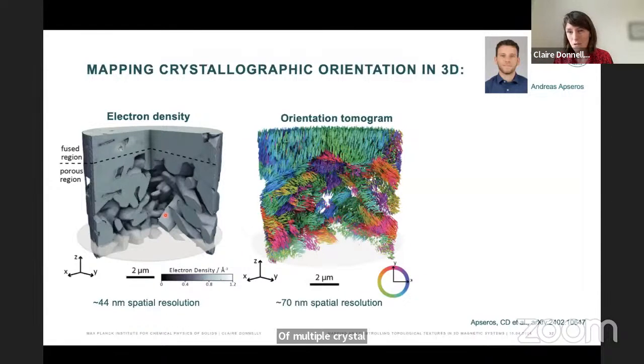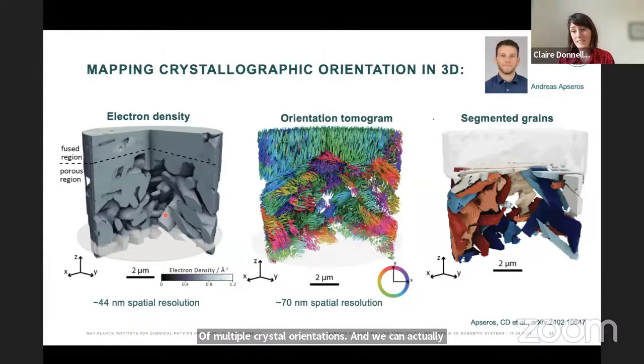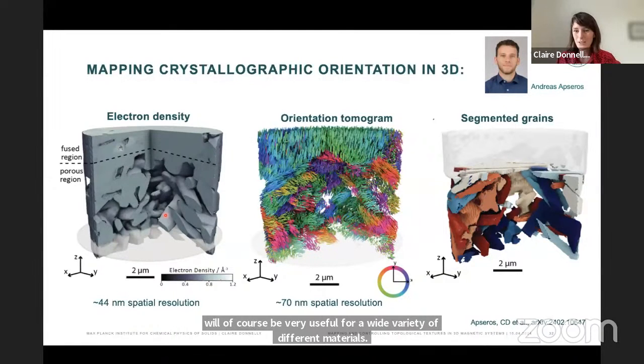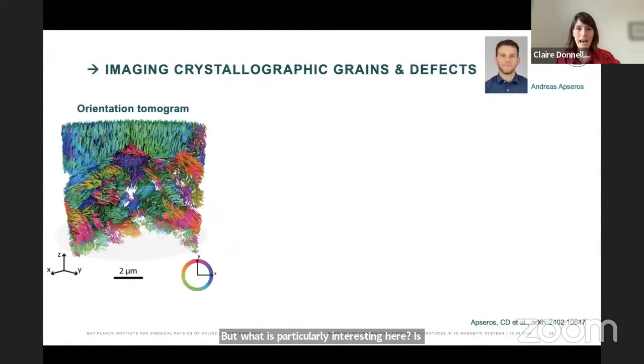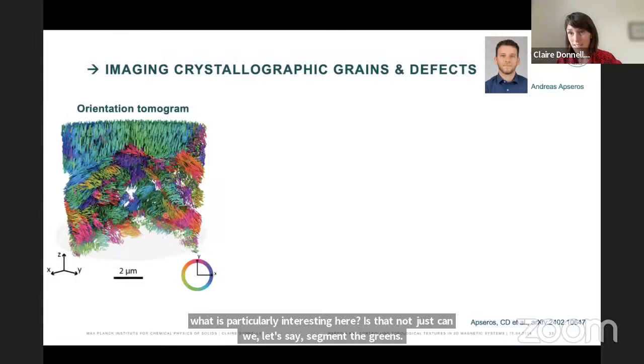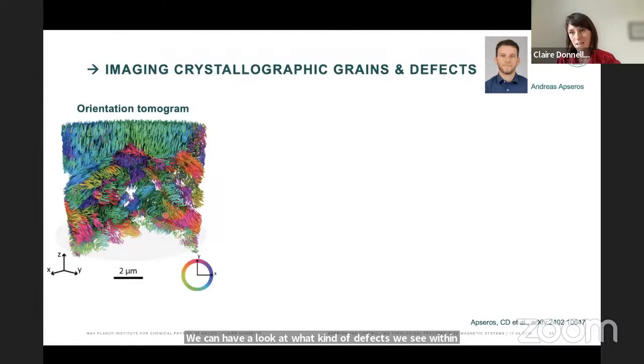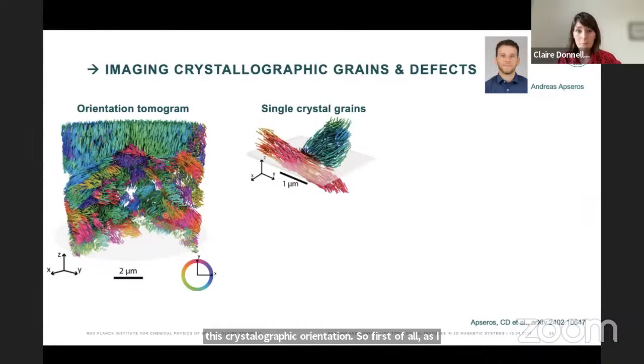And we can actually use this orientation tomogram to segment our data sets, so to identify crystal grains within our system, which of course would be very useful for a wide variety of different materials. But what is particularly interesting here is that not just can we segment the grains, we can have a look at what kind of defects we see within this crystallographic orientation. First of all, as I mentioned before, we can have a look at the grains themselves. So we're able to identify and map single crystal grains, as you can see here, where we have pretty much a single crystal orientation within the isolated piece.